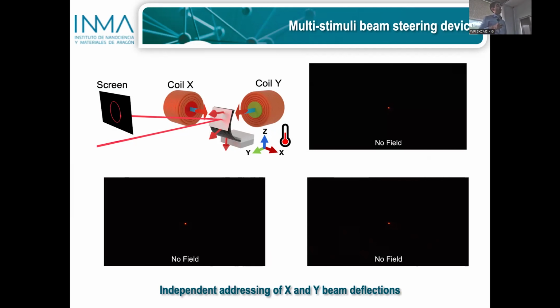But if we fix the temperature, we center the spot at some point, and now we have this point on the screen. Now, we put a couple of coils, one perpendicular to the plane of the film and one from the back, and now we apply a small magnetic field in this coil, you get a bending of the cantilever, and then you get the laser on the screen moving up and down. If now we remove this magnetic field and we apply current to the other coil, then we get a torsion of the cantilever, and then we get a horizontal movement.